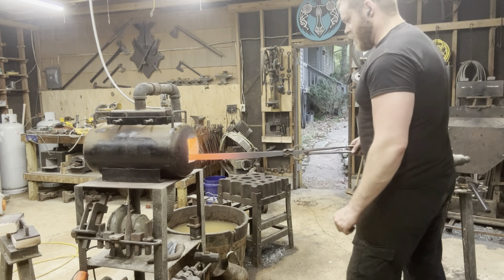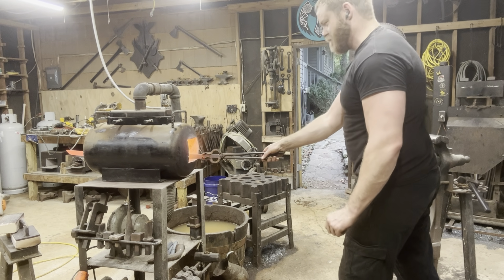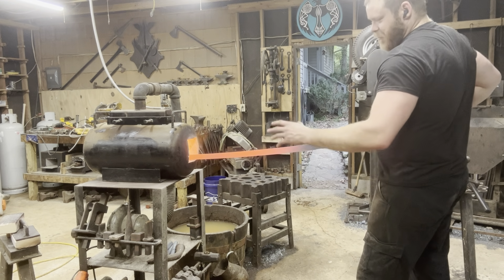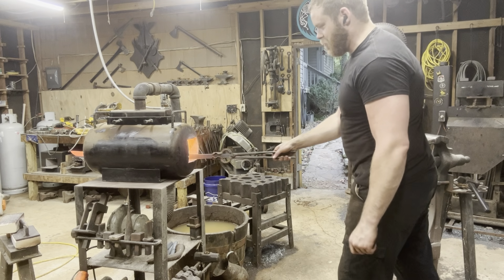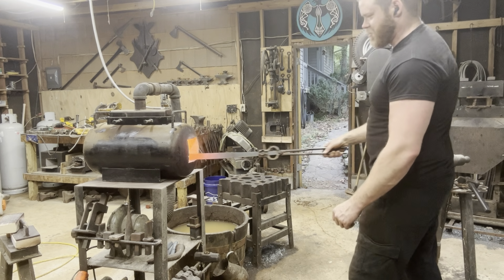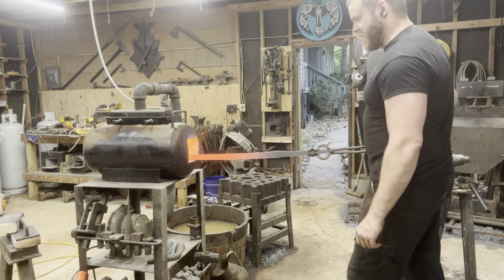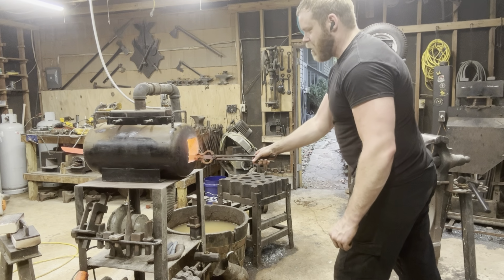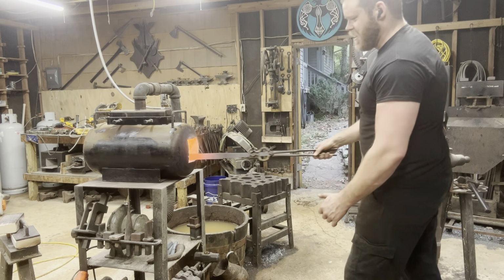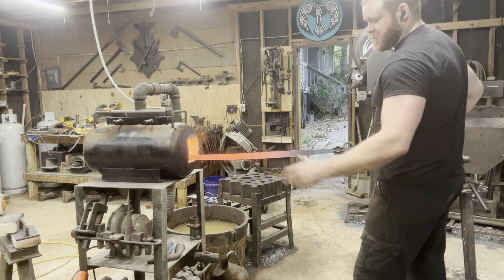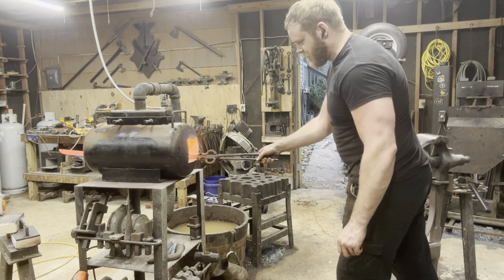Next step is to go ahead and normalize the blade a few times before we quench it. To do that, we need a consistent even heat over the whole blade of about 1500 degrees or so. And to get that, I'm using a technique called painting the heat, where I'm just passing the sword in and out of the forge nice and slow. This is how you heat treat a blade that's longer than your forge.